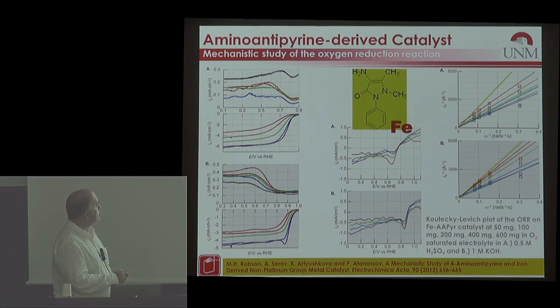The majority of the graduate students want to do this. They want to put as much catalyst as possible on the area, on the electrode, and then record the least possible yield of peroxide. The only thing that means is that you have deviated from the conditions of Koutecky-Levich analysis because you made a brick, not a layer. And the second thing it means is that you just consumed your peroxide inside your brick.